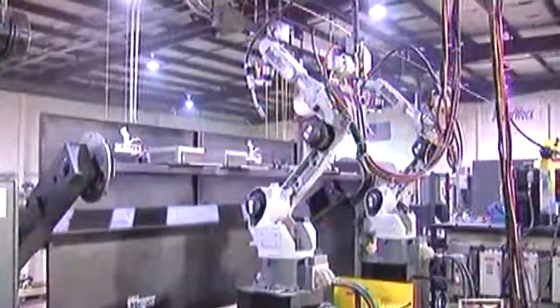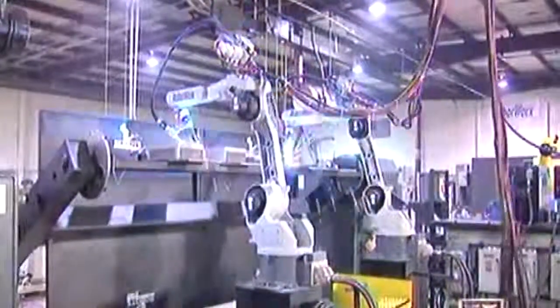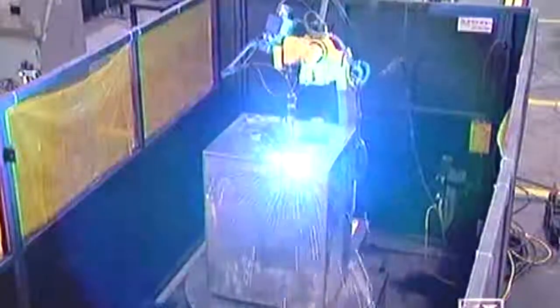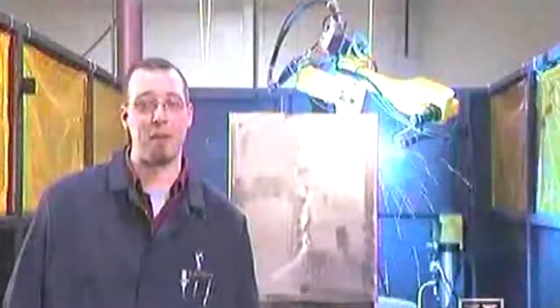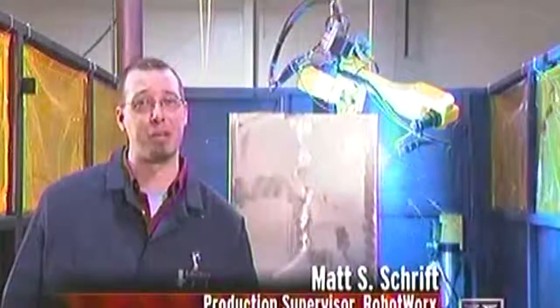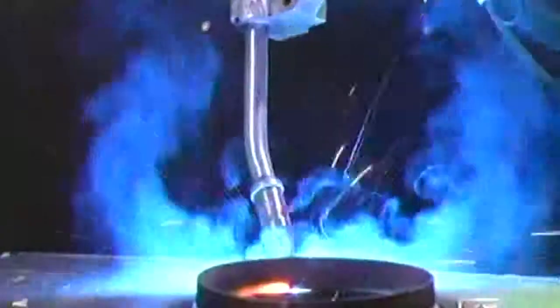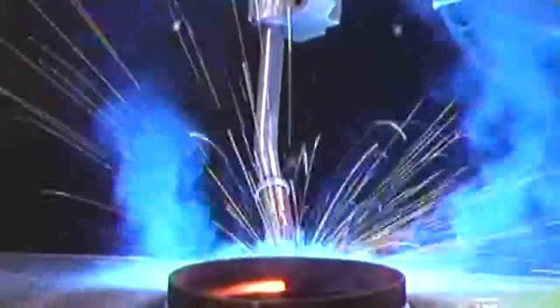The robot can pretty much weld the same speed as a man. Where the payoff is, the robot is always welding. A man has to weld and then lift his hood up and adjust the part and put the hood back down and re-weld again. Where the robot's just going to weld. It might have a 85% arc time compared to a manual of 20%. It took a man about 3 hours to make this particular product. Now that the robot's welding it, it takes essentially about a half an hour to weld the entire part.